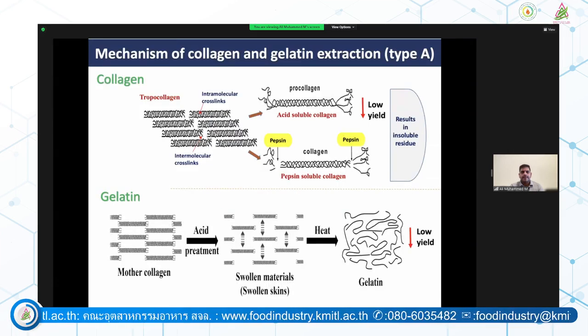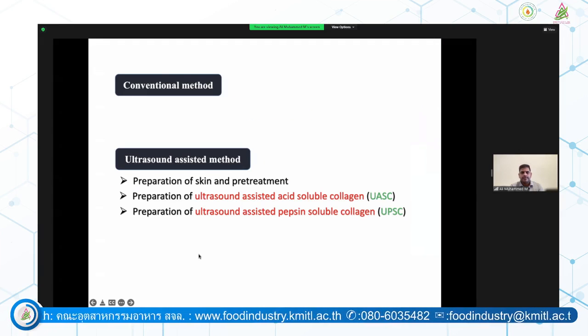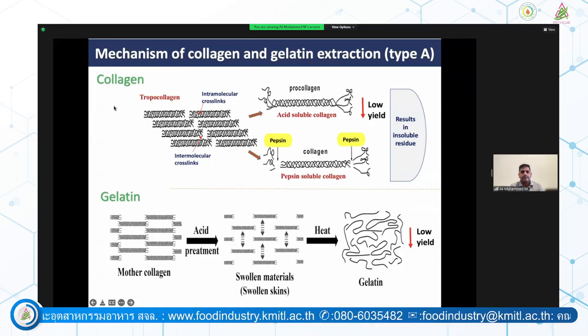As we can see, there is the conventional method, and I have used the ultrasound assisted extraction method. Here you can see a collagen molecule which has higher cross-links. This is from the fish skin, which has a larger amount of cross-links. These cross-links can be solubilized or loosened with the help of acid, and we extract the collagen in a conventional way. This generally has a lower yield, and to improve the yield, industries still use the aid of pepsin, but together these result in an enormous amount of insoluble residue, which is not utilized further. So I am trying to utilize this to the maximum extent.